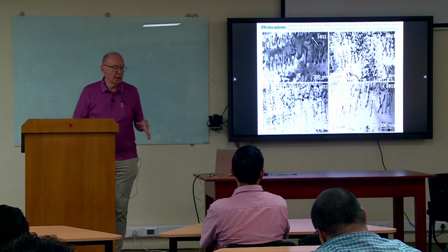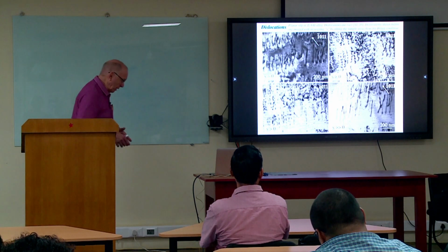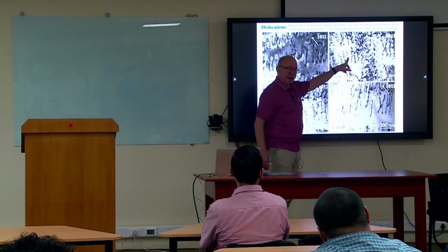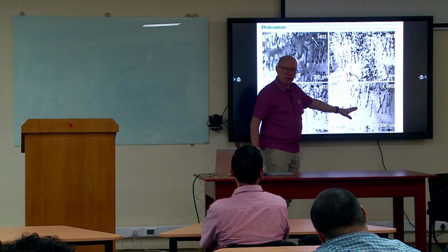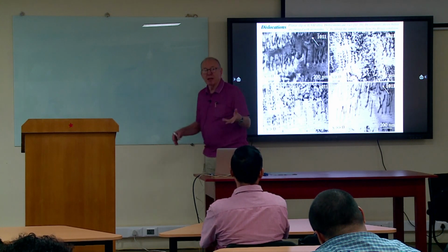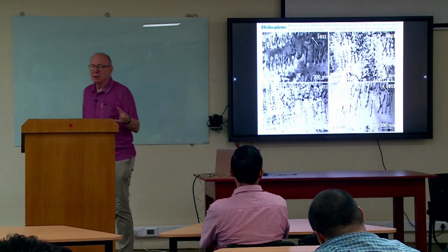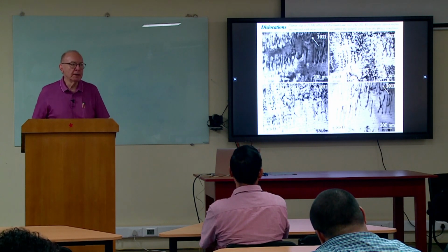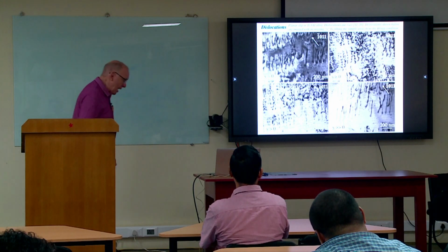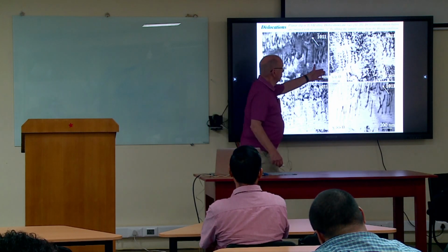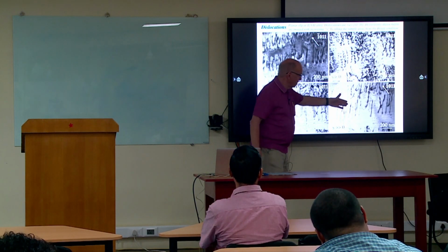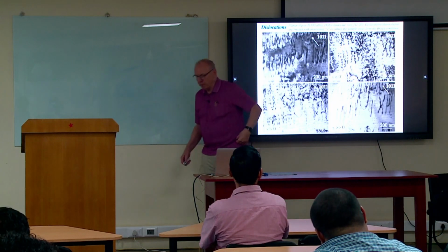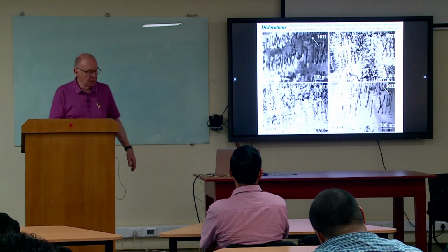And so we can jump ahead and say, okay, this stuff here is dynamical scattering, and this is more like kinematical scattering. So something in the dynamical scattering is giving us these wiggles and fringy contrast. In fact, we like this because this is quite an interpretable image, and we're losing image quality here. So we're getting straighter defects, but we prefer to have the wiggles in terms of being able to do quantitative analysis of these defects.